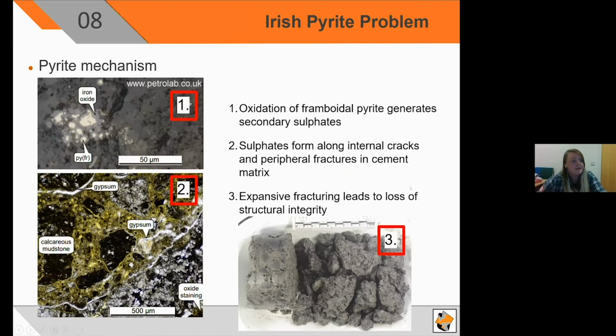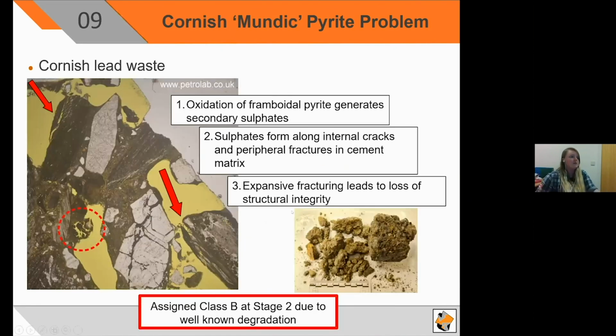So this problem is actually extremely similar to our Cornish Mundic pyrite problem. This is our typical lead waste. Exactly the same premise. The lead waste is mudstones which bear framboidal pyrite. You have oxidation of the framboidal pyrite, which generates secondary sulfates. You can see all these internal cracks opening up near the arrows, spalling into voids. You've also got a sulfide here that's blowing apart, and again, leads to expansive fracturing and loss of structural integrity. So from this, at stage 2, it is automatically assigned a class B because it's due to well-known accelerated degradation.